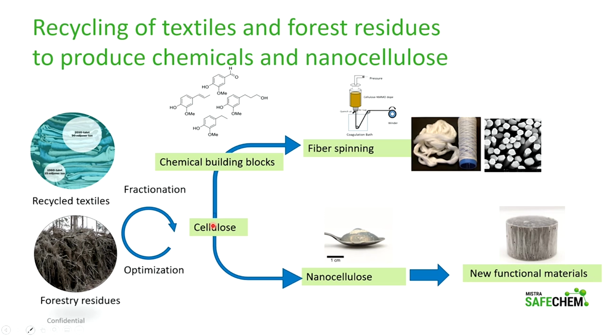If you take the two raw materials we have worked with, recycled textiles and forest residues, we developed different fractionation routes, as you can see here, and fractionated into different fractions, including chemical blocks, which is more chemical based, and also the cellulose, because both sources have cellulose as a common fraction. The cellulose is used to make nanocellulose. For example, in the case of recycled textiles, nanocellulose means both crystalline regions of nanocellulose as well as nanofibers, and then they are further used to make new functional materials.